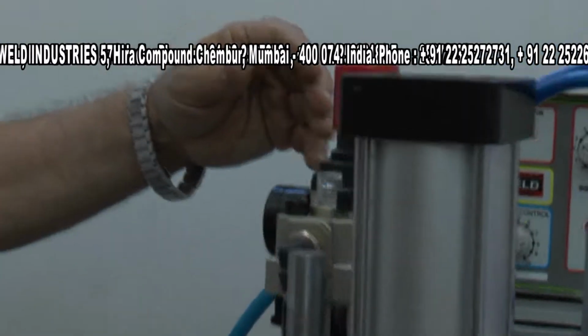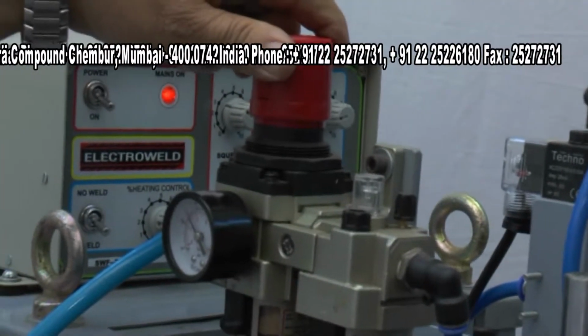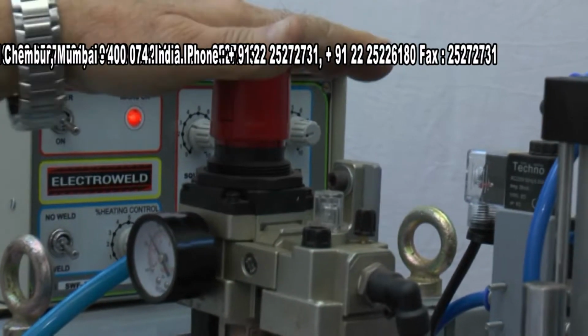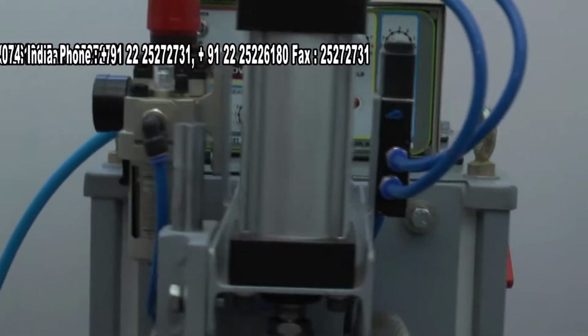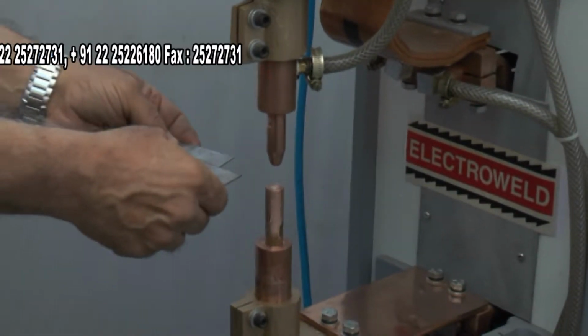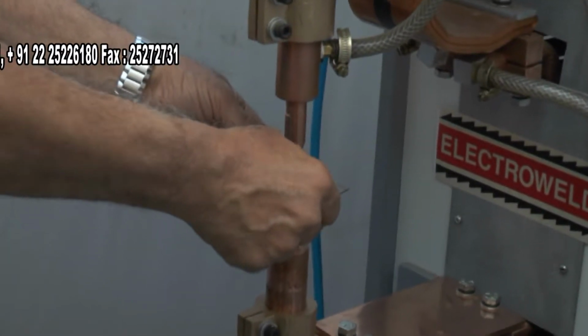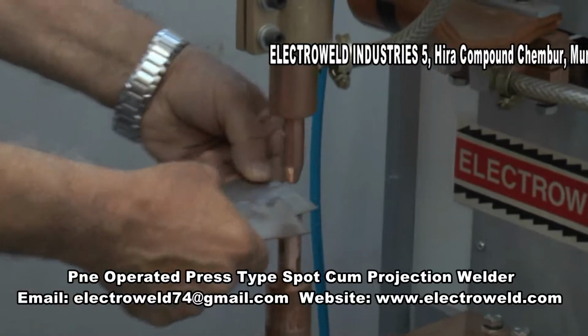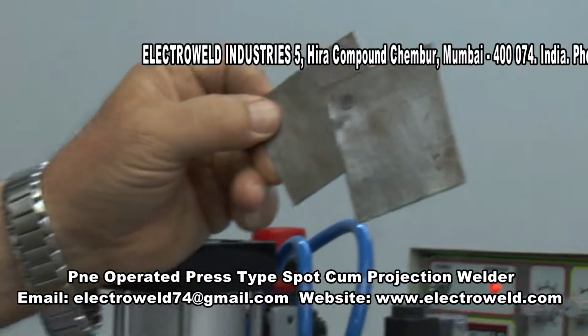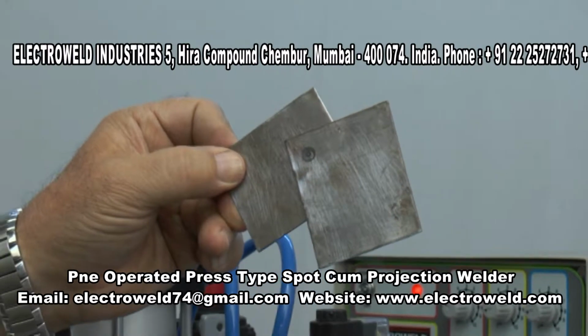Pressure, you can bring down to say about 35 psi by rotating the knob anti-clockwise and then pressing this knob. So the pressure is locked. Now you can spot weld 16 gauge MS components by putting the two sheets together in between the electrodes and by depressing the foot switch. Now you will see the welding will take place, the current cutoff will be automatic. See, this is how it is spot welded. Now this joint will never break.